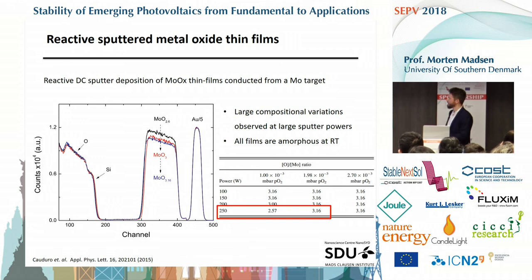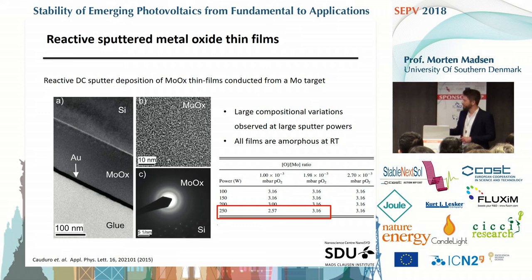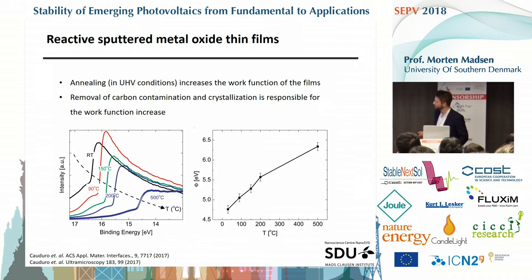What we wanted to do is to introduce these layers into devices and use them as hole contacts. What we see for all these films deposited at room temperature is that they are amorphous and they possess quite low work functions. From TEM, we see basically no crystalline features appearing. When we look at work functions probed from UPS, we see that at these room temperature samples we have quite low work functions.